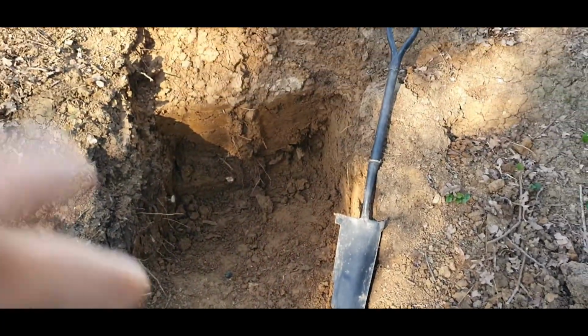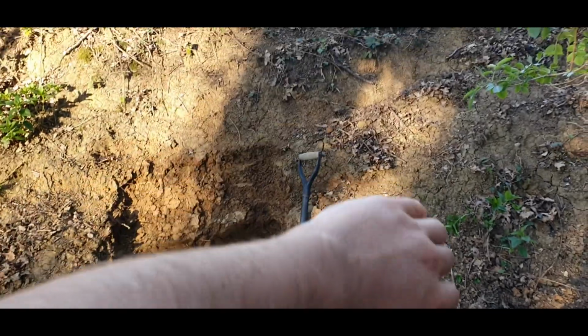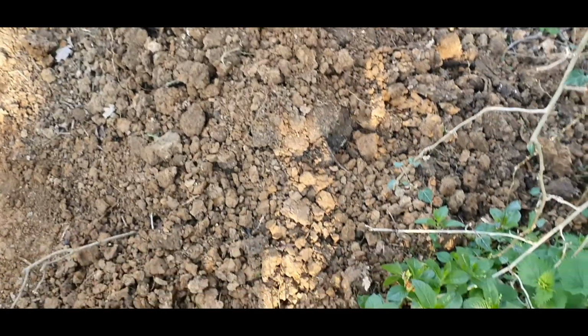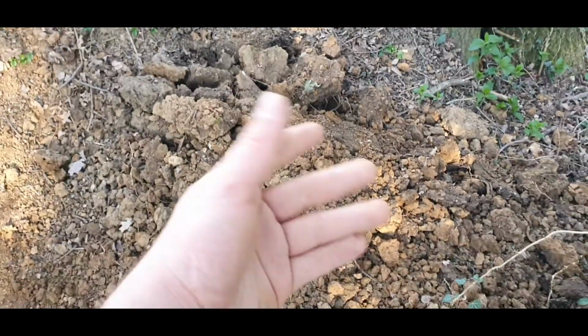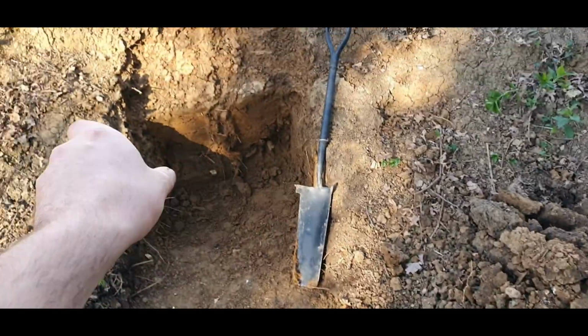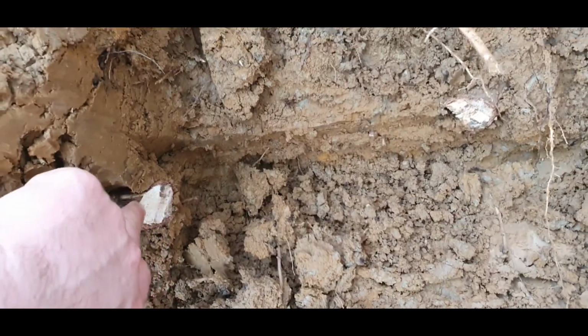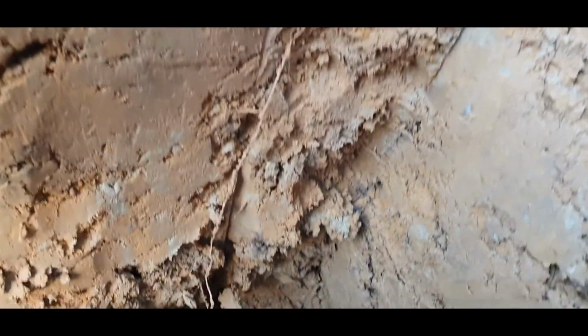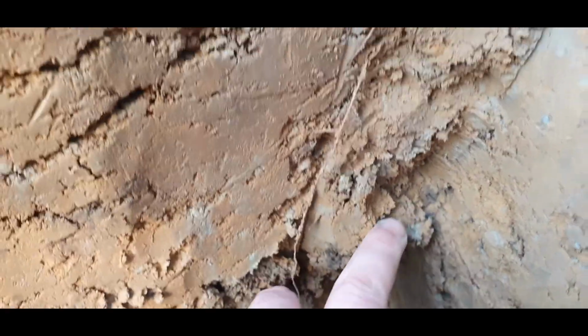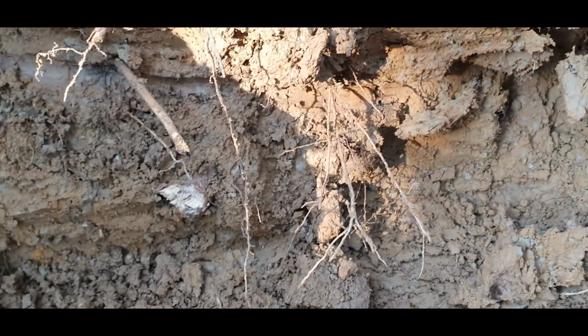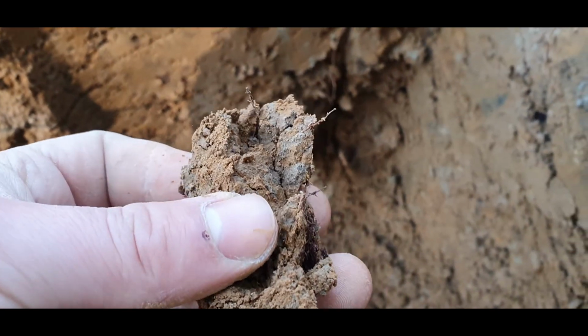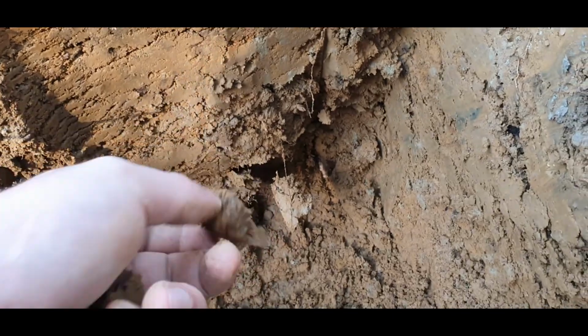So getting deeper and deeper into the embankment now, and eventually I'll be able to sit my kiln inside there, and that will offer an extra layer of insulation. Anything that's not really very clean clay I'm throwing over here, which I'll then use as a cob mixture to mortar my bricks together. The only issue I've got is roots that come through, and they're pesky and very thick, difficult to cut through. I'm keeping my eye out for larger pieces of the grey clay, because I'd very much like to be able to isolate it and make a lighter slip, but it's just so finite that it's difficult to isolate. If you look, specks of grey all the way through it, veins of it. Very difficult indeed.